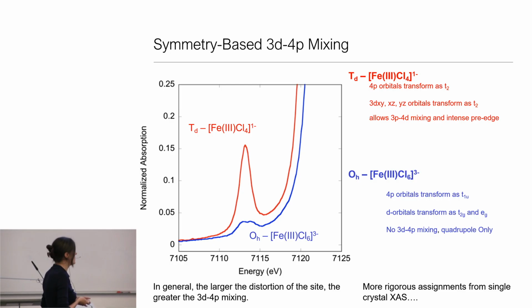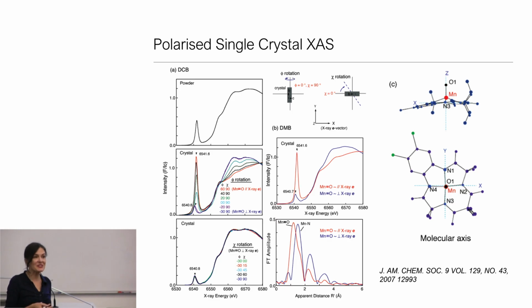And you can actually assign this much more rigorously from single crystal experiments. I'm bringing this up just because it's something I particularly enjoy, but not that I expect many people will want to do this. But these are old single crystal experiments we did just to really rigorously show how these pre-edges can be assigned. And so at the time, computationally, we had sort of said from group theory considerations, I'm in C4v symmetry. I should have an intense mixing that occurs in the Z direction, where the pz and dz squared can mix, because I have a very short manganese oxo bond, right? This would be covalently mediated. And to actually test this hypothesis, we looked at what happened, and we showed that when you had your X-rays along the manganese oxo bond, you had maximum intensity.